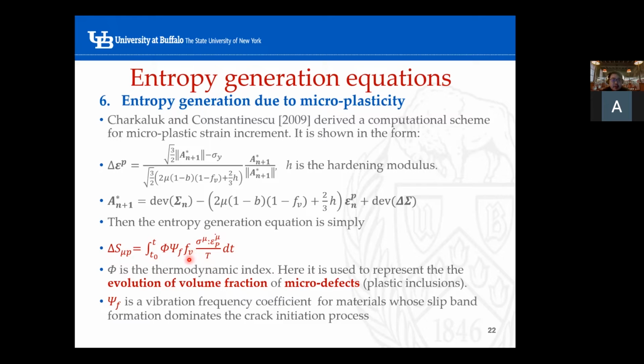Because we're only accounting for the microplasticity, and microplasticity happens at the micro defects, we have to times this FV coefficient. Phi is accounting for the evolution of the micro defects, evolving from 0 to 1. So far it's just the same equations as I mentioned yesterday. However, here I'm adding another coefficient called psi sub f.